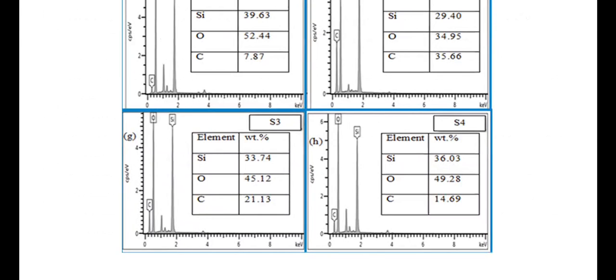Okay, so this is the EDX which we have done on the binder system alone, where you can see that when the Sylgard weight ratio is increasing, the carbon content is increasing. Then it starts to decrease because higher cross-linking is taking place, and the carbon ratio becomes lesser. This is another evidence to it.